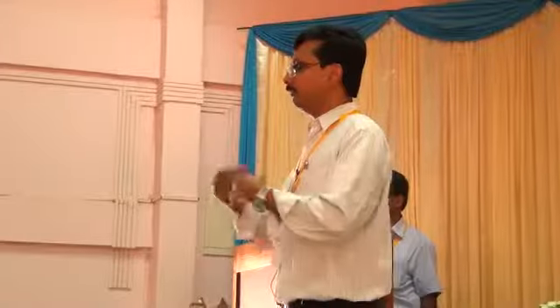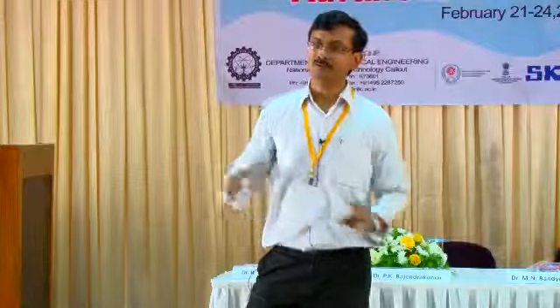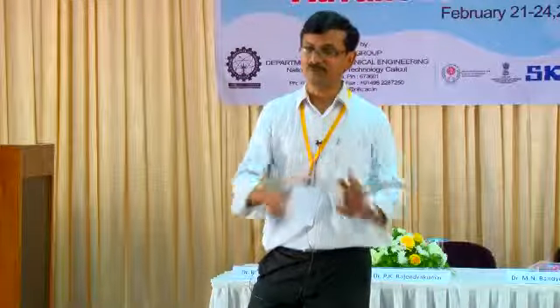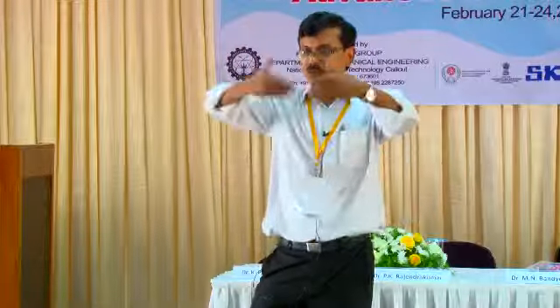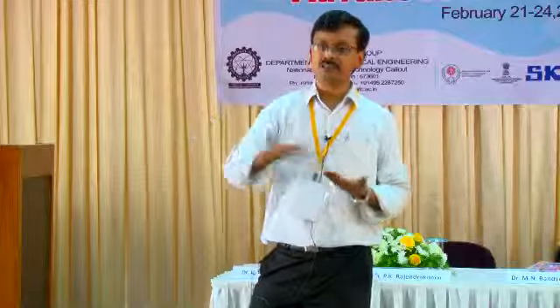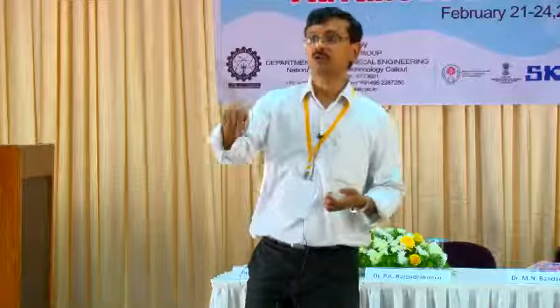All we know is after doing the experiment, when we did the experiment with gallium, we know there was more gallium concentrated close to the surface than far away from the surface, the subsurface if you want to call it. So from there we know that something has happened. So we assume that it is made of a different layer. The TEM does not give any difference in crystallographic orientation. Yeah, we were not able to see it.